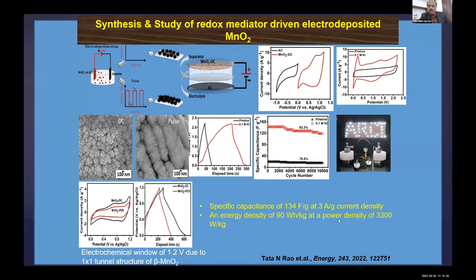And then you can see here, I take an electrolyte with a redox couple which has very high cycle stability. I went up to 10,000 cycles with only 80% retention, but that is good enough for a supercap. And then 134 farad per gram at 3 ampere per gram current density.